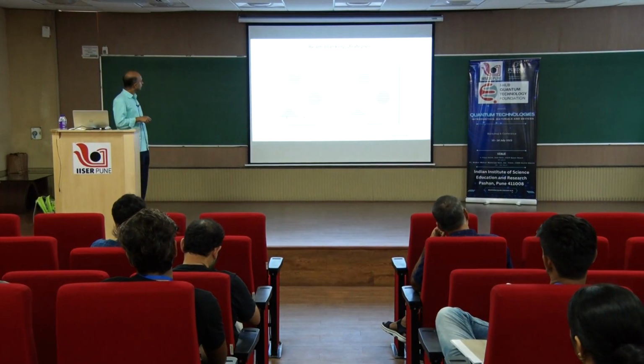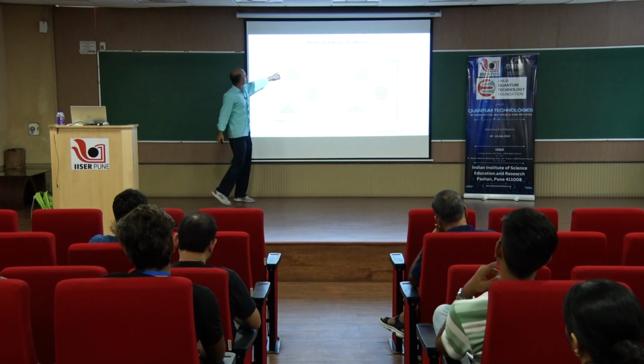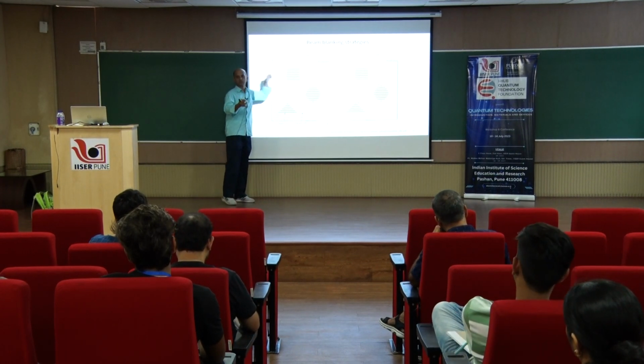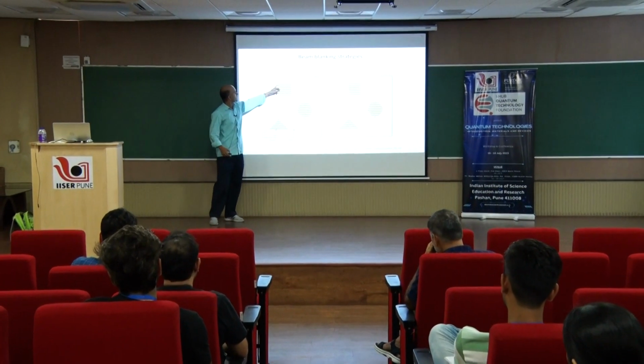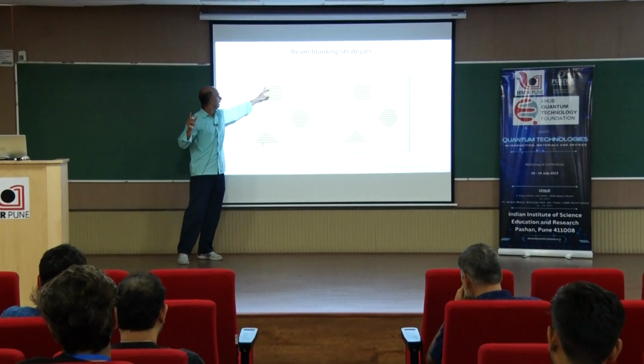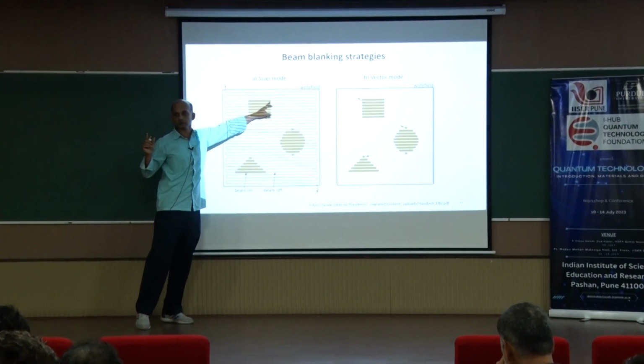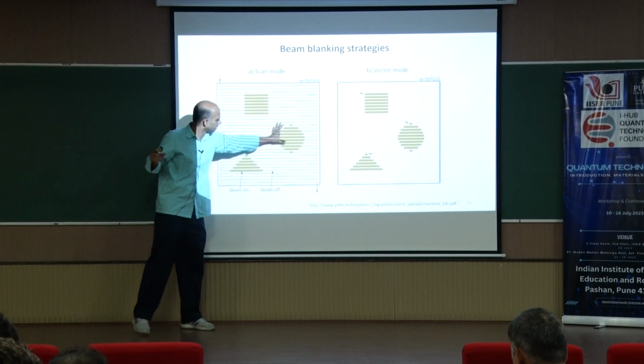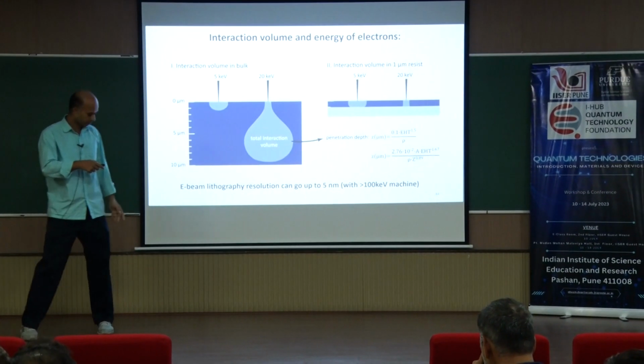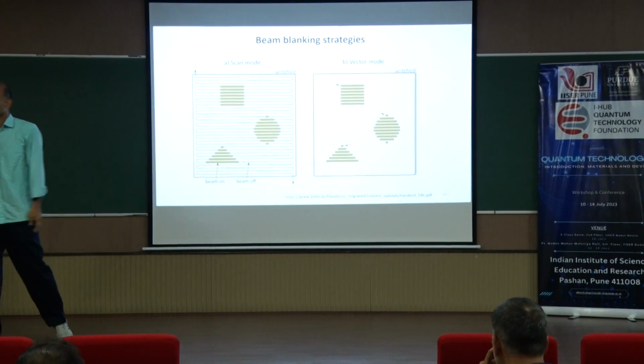You basically just consider the scan mode; forget about the vector mode, generally we do not use vector mode. In the scan mode your beam is scanning here. Up to this region the beam remains blanked, it does not fall on the substrate. Only in this region it opens and the beam falls on the substrate, and then it closes. It just scans like that, and finally you get this kind of pattern.